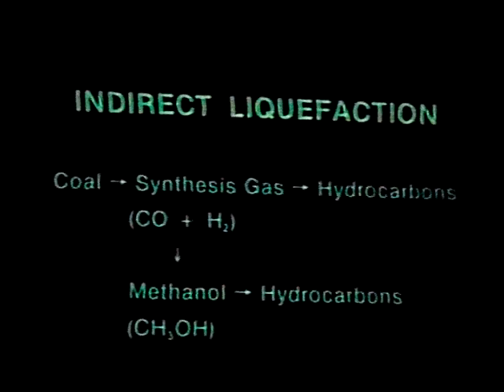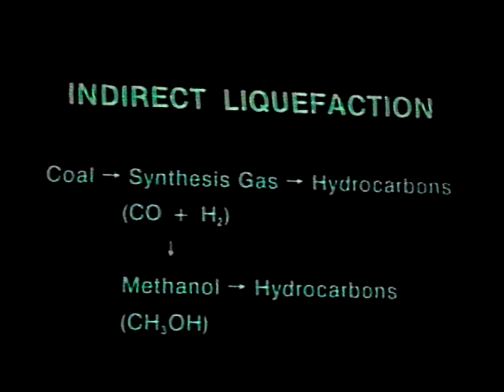As you know, indirect liquefaction is concerned with converting coal to liquid hydrocarbons or oxygenated fuels through synthesis gas. After making synthesis gas, one can go directly to hydrocarbons through Fischer-Tropsch catalysis using a group 8 catalyst, or one can go to methanol, and using ZSM 5, one can go to high-octane gasoline. Our experiments were connected with combining the group 8 catalyst with ZSM 5 and trying to achieve a conversion to high-octane gasoline over a single catalyst from syngas.